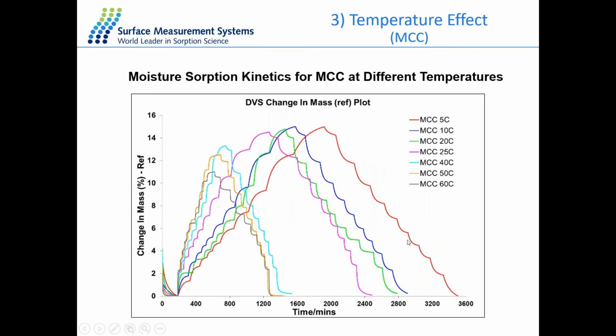And here are the results for different temperatures. Different colors are for different temperatures, and between 5 to 25 degrees, the moisture uptake at a particular relative humidity doesn't show a significant difference, but the time for reaching equilibrium is much longer in the 5-degree experiment compared to the 25-degree one. For the results at higher temperatures, the 40-degree, 50-degree, and 60-degree ones, with the increase of temperature the water sorption capacity decreases, which is probably due to a structural rearrangement inside the microcrystalline cellulose material. However, the kinetics still keeps increasing with elevated temperature. So the experiment time for the 60-degree run, which is about 1 day, is about 3 times faster compared to the 5-degree one.